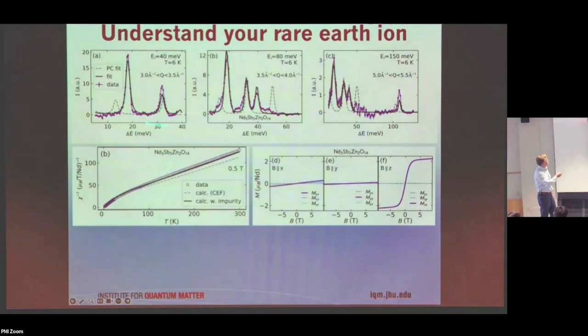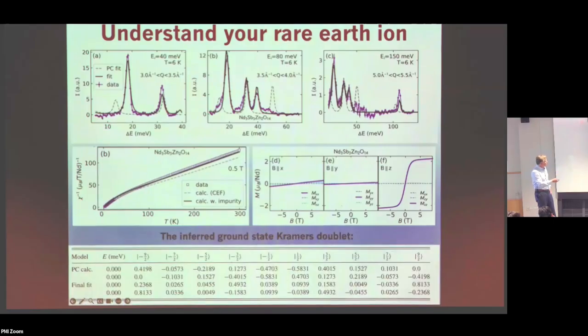Now you do some fitting of the spectra as well as magnetization measurements, both susceptibility and saturation magnetization. You actually need to combine these things to get a reliable result. We've been burned once, and we're trying not to be burned again. But by combining those, you can really get the whole composition of the ground state Kramers doublet. In this case, it was a neodymium ion.